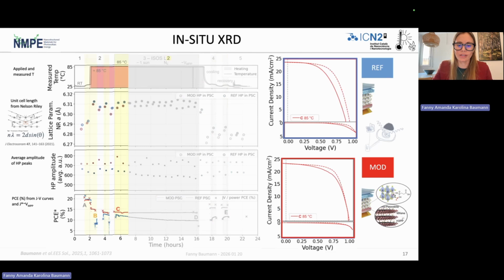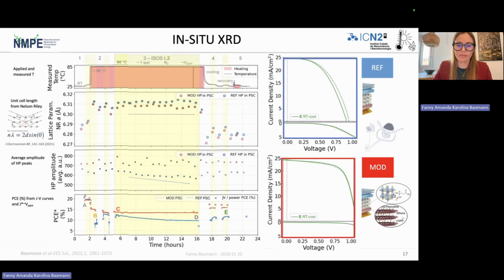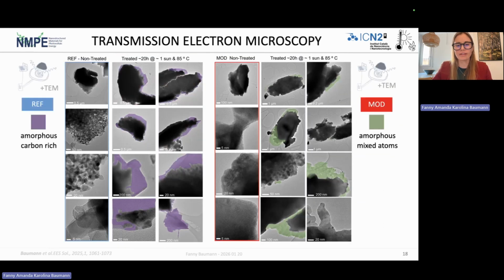So in order to do that, I just quickly have to go through this. Okay, in order to do that, we did the postmortem TEM. So we split a device down the middle and treated half of it. And in this same device, we looked at the samples treated at the identical conditions as the testing for 20 hours.